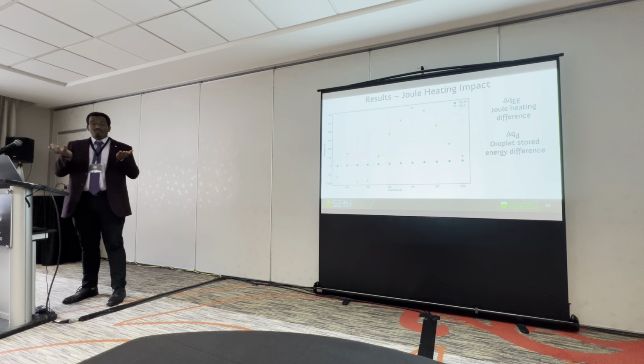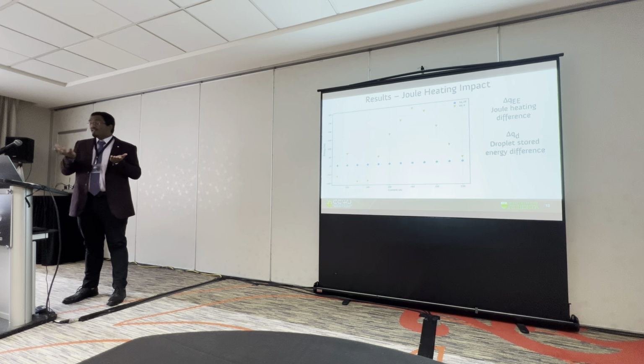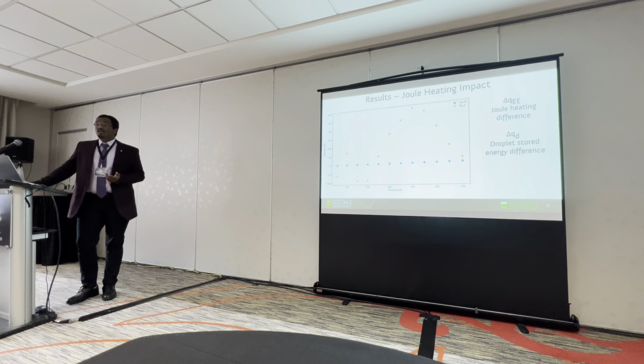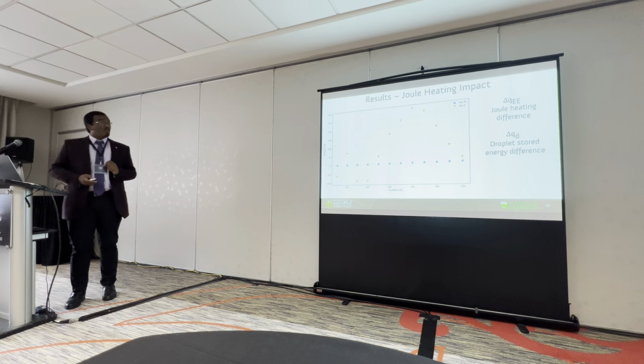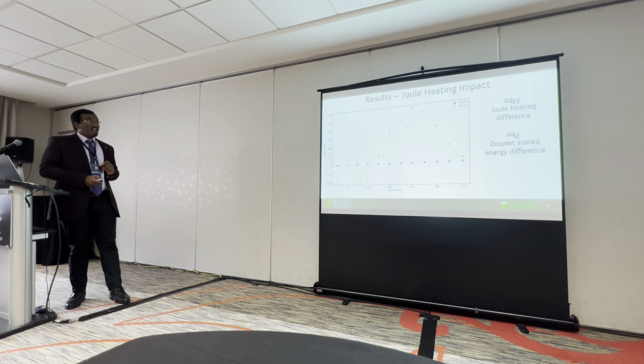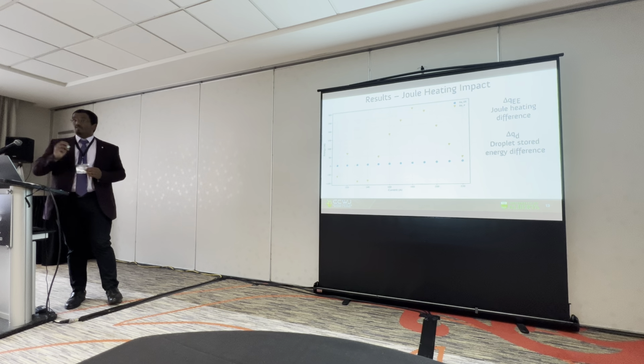Because if you provide similar power, we can think of some other reason, but when you have this lower power delivered to 5183 and it has a higher wire feed speed, the only reason it could be is because 5183 also has much lower droplet temperature than 1100. So the lower droplet temperature of 5183 can explain why we have a high wire feed speed, even though lesser power is delivered to it.